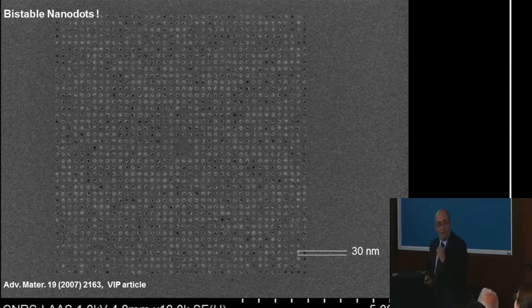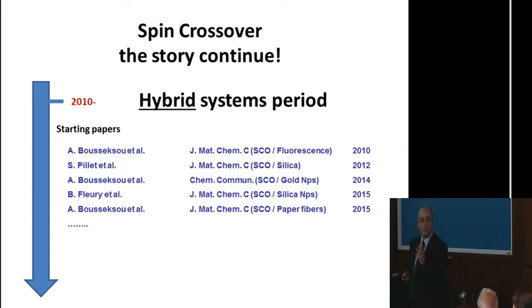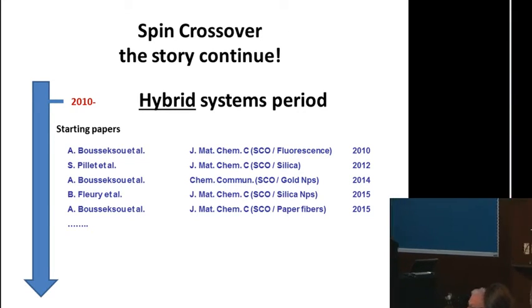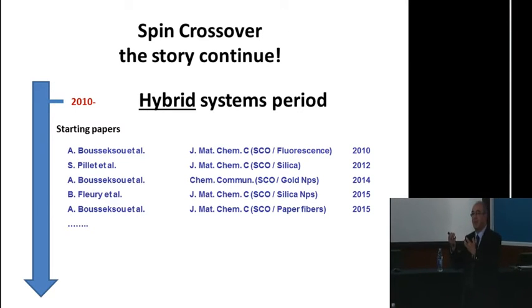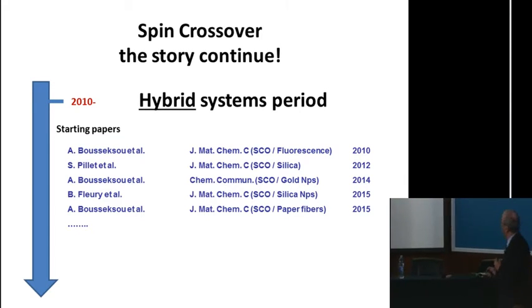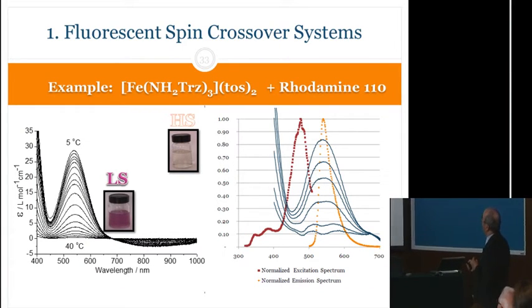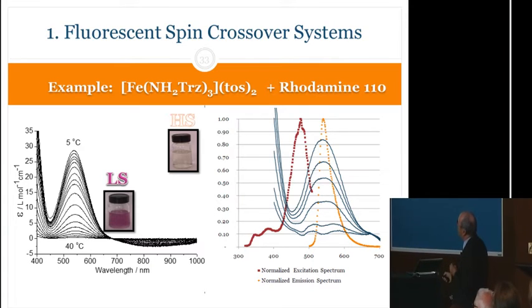So then started the hybrid period. The hybrid period is to combine, for example, spin crossover materials with luminescent systems and try to find if we have any synergy. You will see that by using a combination between spin crossover materials and luminescence, we can read the change of the properties in our dot and see whether we have the hysteresis loop or not. So then what we did is the following. If you take this spin crossover system here, if you look at the optical properties of the spin crossover, in the low spin state, it's pink here, it absorbs in the green region at 530 nanometers, okay? In the high spin form, it's transparent, there is no absorption.